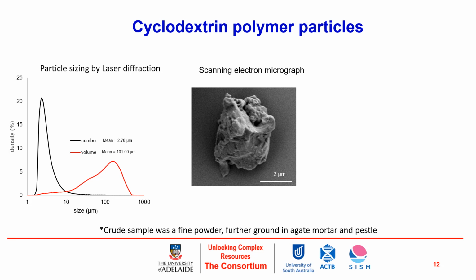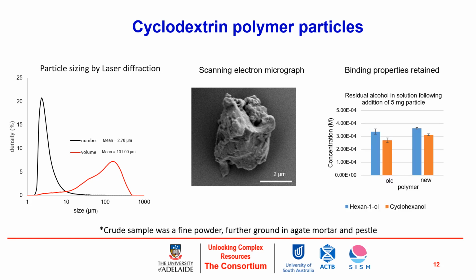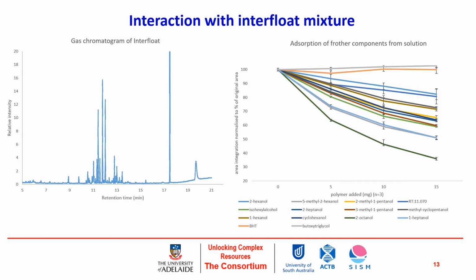Now this was still a prohibitive size for utilization on the quartz crystal microbalance system because they were simply too massive, and that was going to be of detriment when using such a sensitive technique. However, they were useful for coupling with other analytical strategies to determine how they interact with the individual components from Interfloat. So what I'm presenting here is an interaction with the Interfloat mixture as represented using gas chromatography mass spectrometry. The left-hand side of this slide shows a chromatogram which identifies the multiple components in the Interfloat mixture as it comes from the bottle.